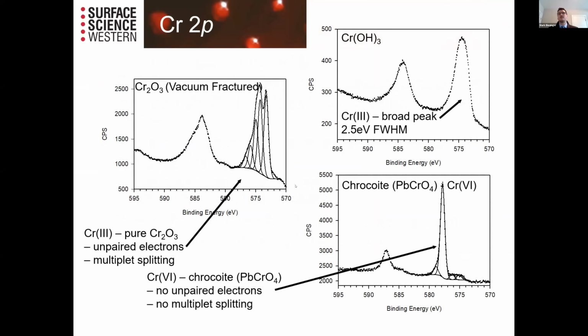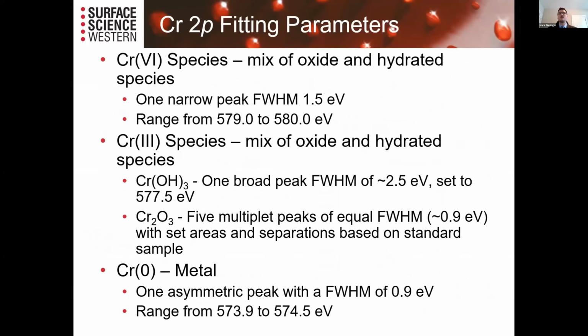And so how do we go about doing this? We take a series of standard samples, do quality analysis. We devise peak fitting routines for each peak. And so that's what this looks like, where you have, for say, chromium 6, a single peak because it has no multiplet splitting. You set its full width half max. You set its binding energy range.